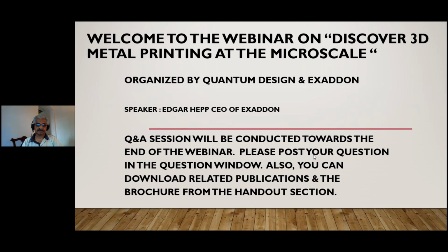Not all metals can be combined, because as we're using an electroplating process, it could happen that we dissolve the other metal. If, for example, aluminium and copper will not work, because if you would print on aluminium, the copper will be reduced, but the aluminium will also be reduced, so it will disappear. So you cannot combine everything.